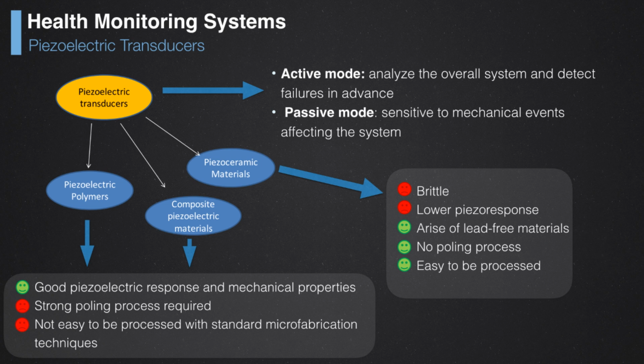The most used one is the piezoceramic material. Ceramic materials are very brittle. They are generally metal oxides. They have quite good engineering properties. That means that with very low variations of the thickness or the shape or the volume of the material, the voltage generated on the surfaces of the device is high enough to be read without too much effort from the electronic point of view.